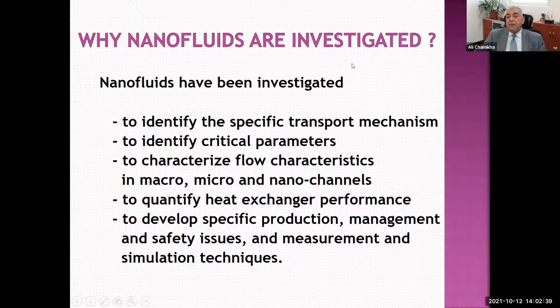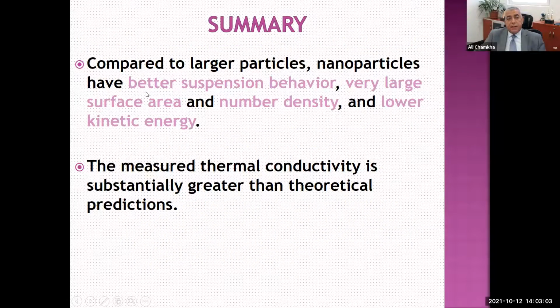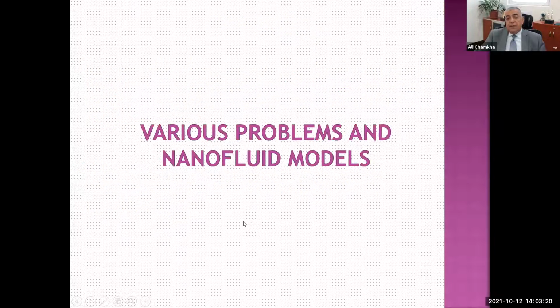Why are nanofluids investigated? They have been investigated to identify the specific transport mechanism, to identify critical parameters, to characterize flow characteristics in macro, micro and nano-channels, to quantify heat transfer performance, to develop specific production, management and safety issues, and measurement and simulation techniques, and others. In summary, compared to larger particles, nanoparticles have better suspension behavior, very large surface area and number density, and much lower kinetic energy due to the low mass they have. The measured thermal conductivity is substantially greater than theoretical prediction in reality.